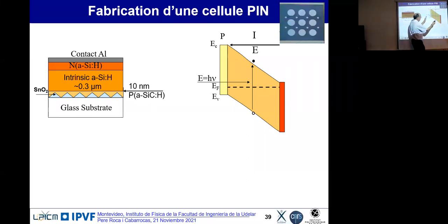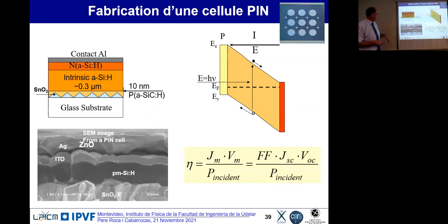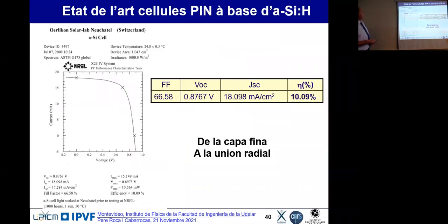So you can view this as the space charge region in the PN junction. In the PN junction, you have a space charge region, and then you have 100 microns, 200 microns of good material. We don't have that here, but it's a thin film, which has a higher absorption coefficient. So even if the layer is thin, it can still absorb the light. So optics is important. And then you make the separation, and then you get the efficiency, and that's the cross section. So this is my PIN, and when I want to go to efficiency, it's limited to 10%. I could say that we can make tandem cells. You probably could go with a lot of effort to 20%, but not 26.